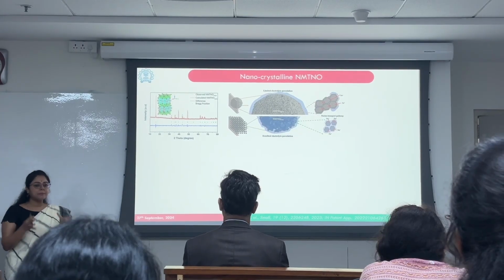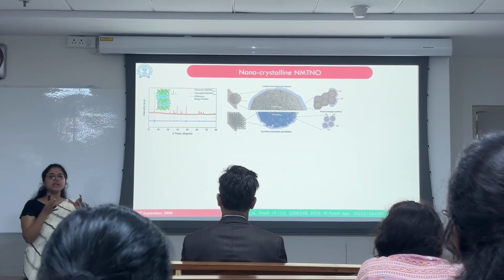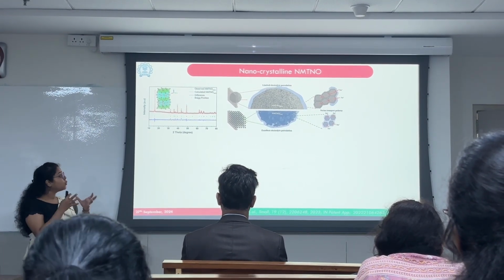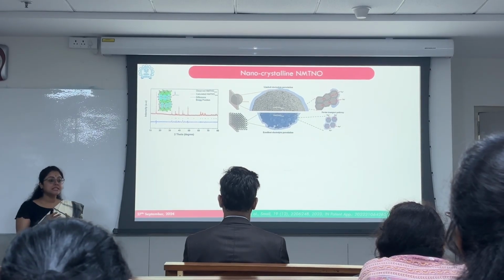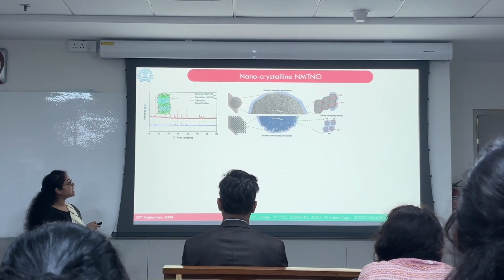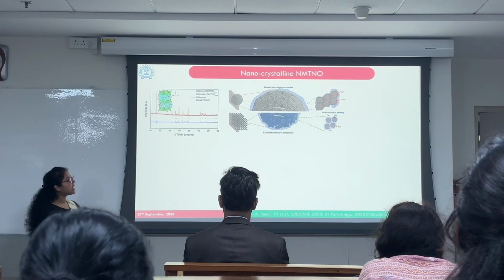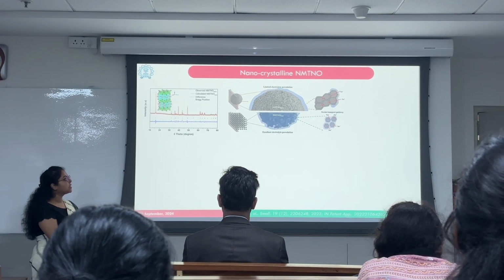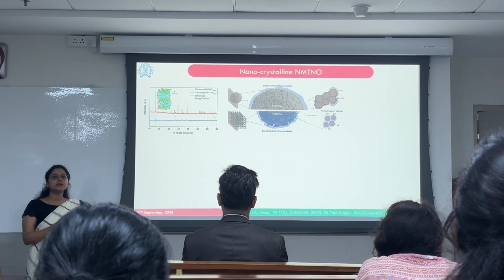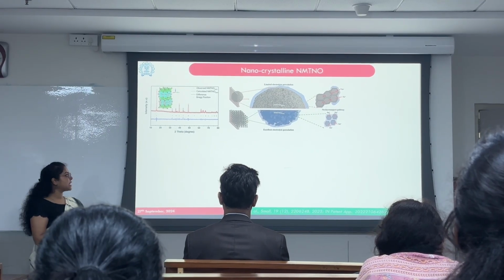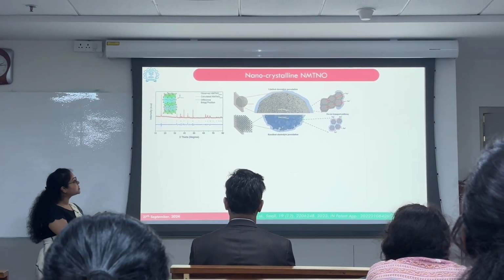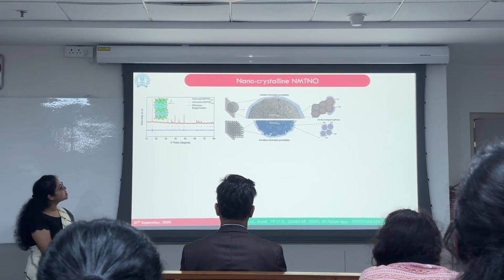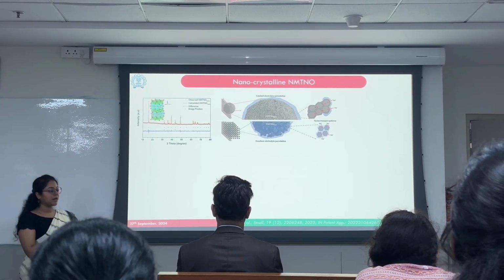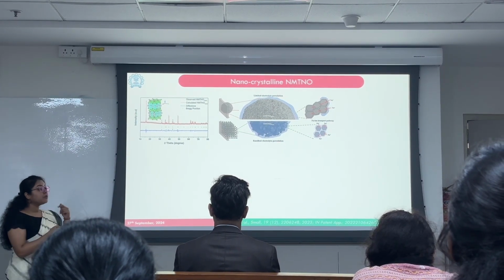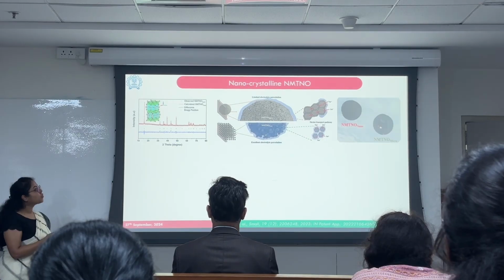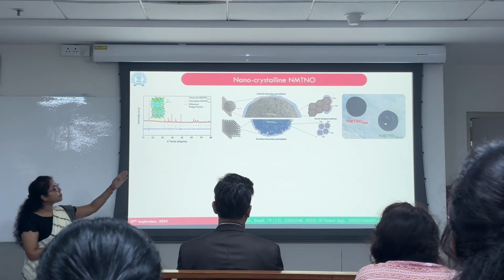So we hypothesized that the NMTNO nano would actually make secondary particles which would be quite porous in nature, leading to excellent electrolyte percolation and enhancing the sodium ion transport pathway. However, for the secondary particle formed out of the micron-sized NMTNO, the electrolyte percolation would be limited only to the surface of the secondary particle.